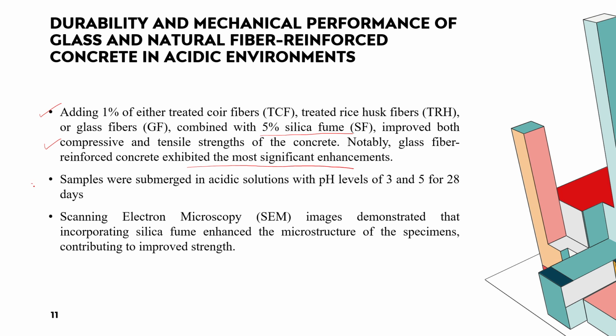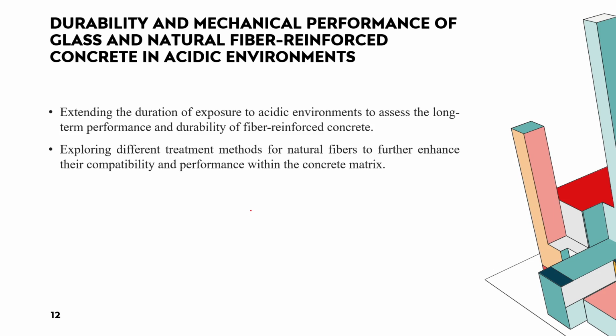For the acidic environment, they prepared the samples and submerged them in acidic solution where the pH was 3 and 5, and kept the samples for 28 days. Also, they performed SEM that demonstrated that incorporating silica fume enhances the microstructure of the specimen, contributing to improved strength.